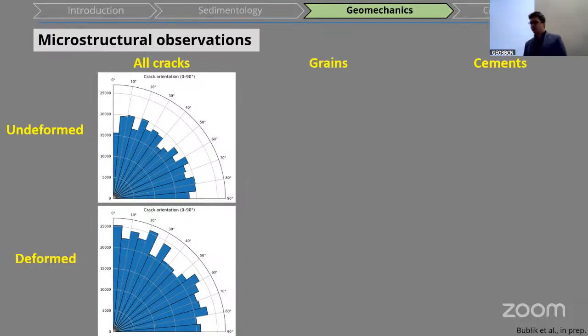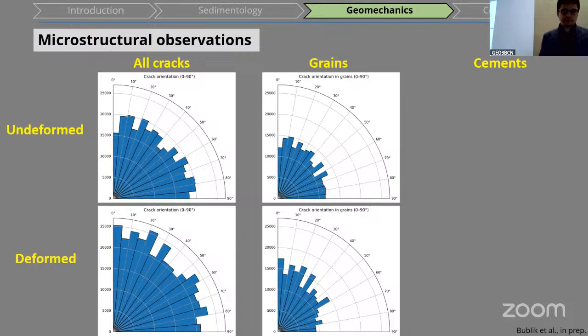So that's a good sign that if we do deform our samples, there's cracks forming. So that means that if we look where those cracks occur, that may also help. If you look just at the grains, you can see there is cracks forming in the grains more as well. So you can see before in the undeformed sample, the orientation of the cracks in grains was relatively random, but you can see that after our deformation experiments, the cracks in grains are more aligned with the stress that we put in them during the experiments.